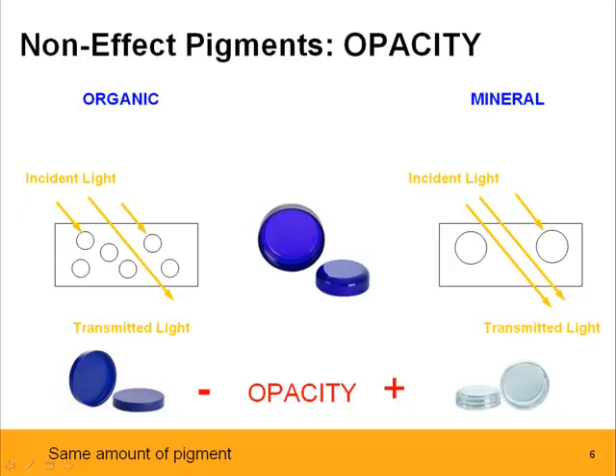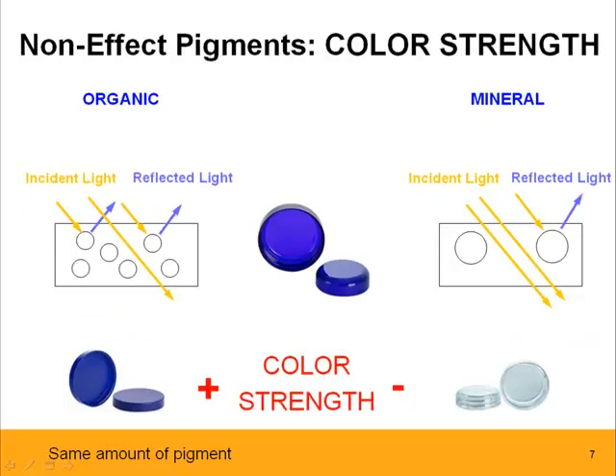Very similar, the same thing happens in regards to color strength. The organic pigments, well distributed, will be reflecting a lot more light back, and therefore have stronger colors, the dark ones in that respect. And as we will see later on, also the ones that are a little bit more difficult to color change, of course. The minerals on the other side, because there are fewer elements for light to be reflected back, will not be as strong when it comes to color strength for the same amount of pigment.